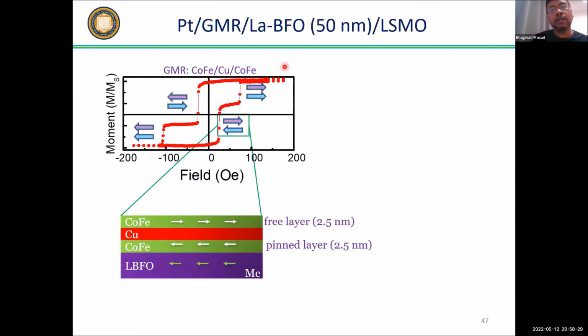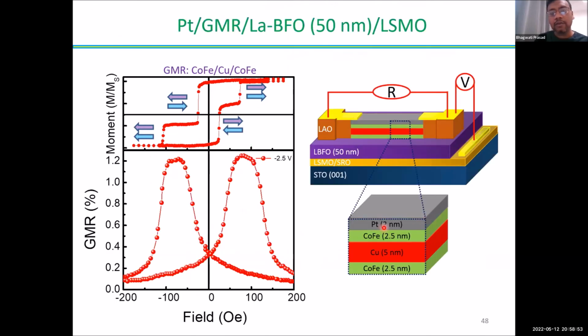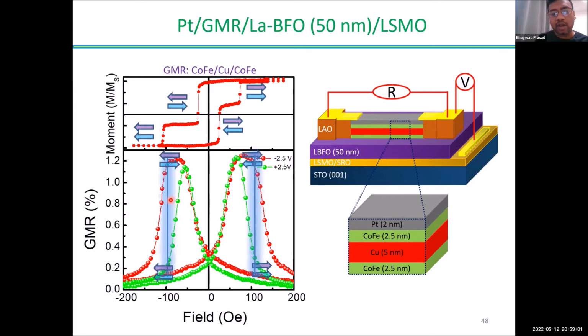We have doped the BFO with lanthanum, reduced the film thickness to 50 nanometer first, and then made a GMR structure, a spin valve structure, with the same thickness of cobalt iron top and bottom. You see there's a split loop. The bottom cobalt iron has a higher coercive field than the top one because it is exchange coupled with the LBFO, and then we measure the GMR. This is GMR at minus 2.5 volt, and when you apply plus 2.5 volt, at 100 Oe, you can switch the device between the antiparallel state and the parallel state.